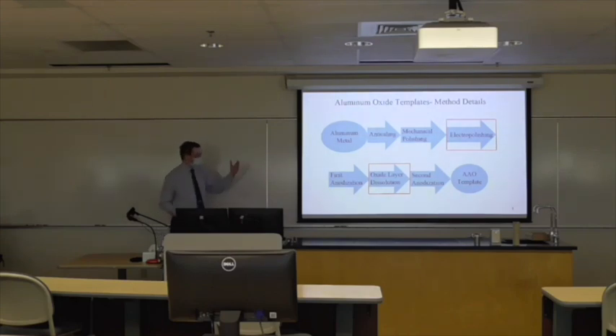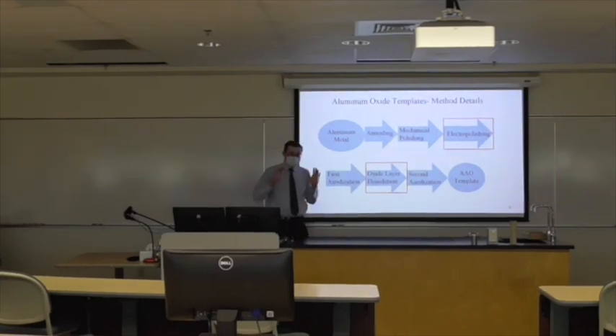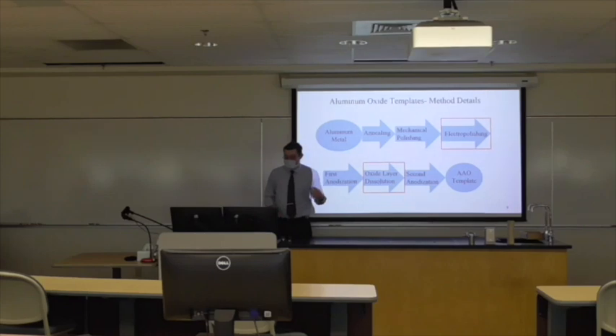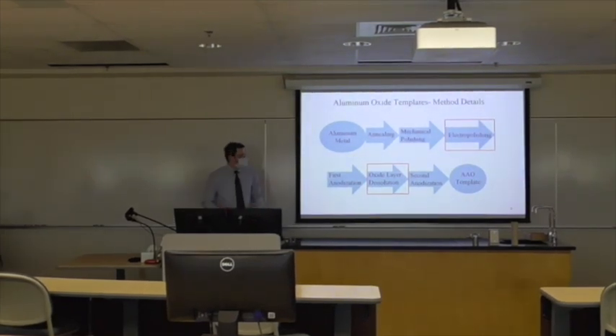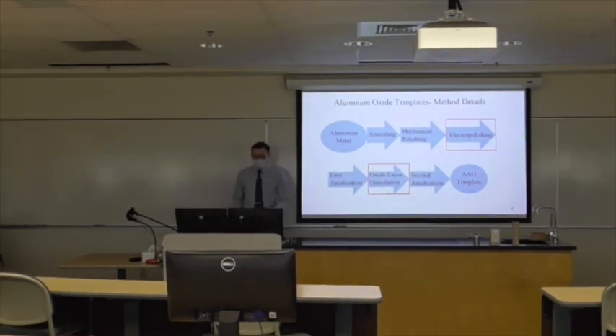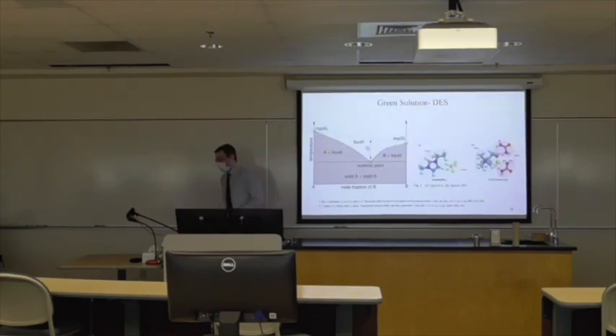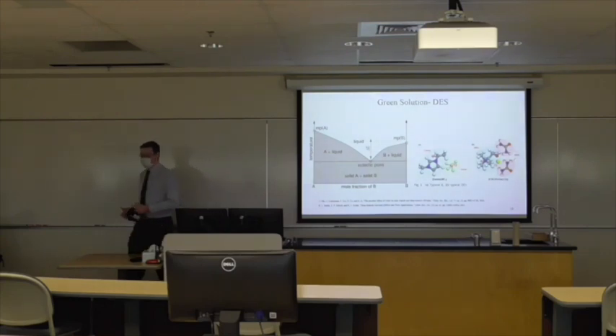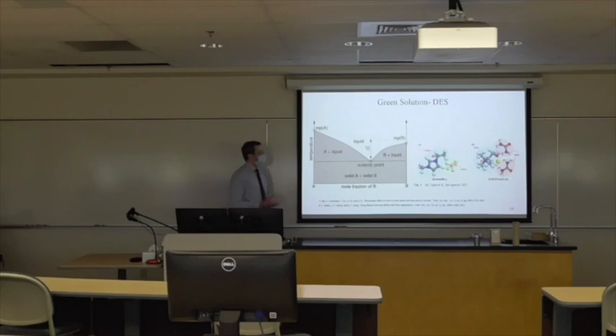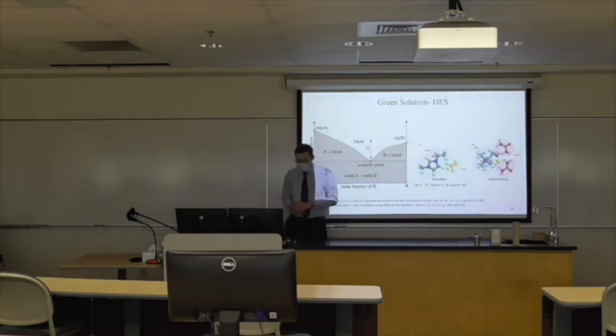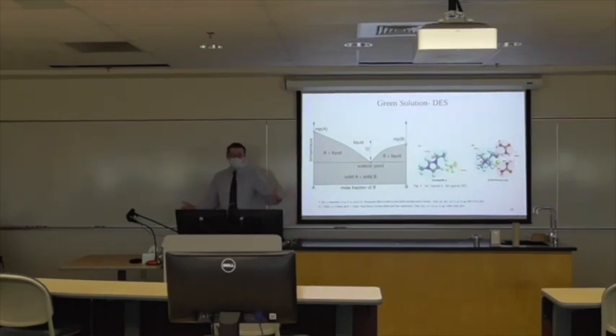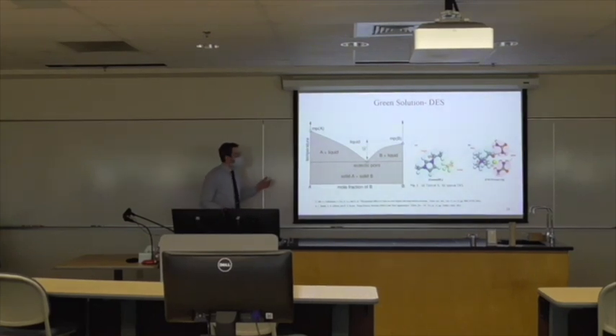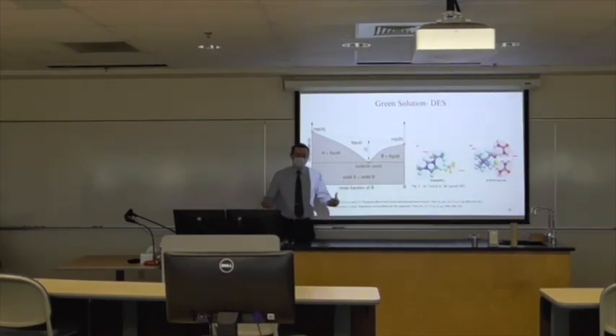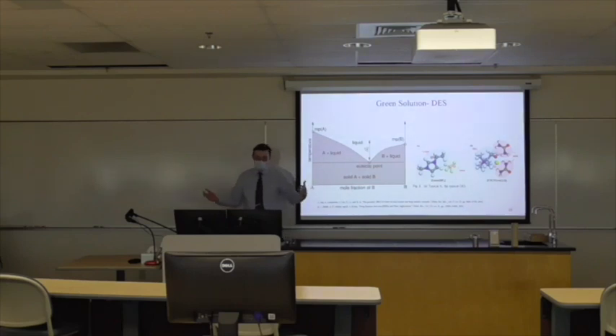So we have sort of our scheme here. What are the things we need to change to make this better? Well, we want to change the electropolishing and the oxide layer dissolution steps. One thing that is pretty recent, that's a really interesting concept, are deep eutectic solvents. Many of them are green, and they're green solutions in both the chemistry sense of a solution, but also a solution like for a problem.